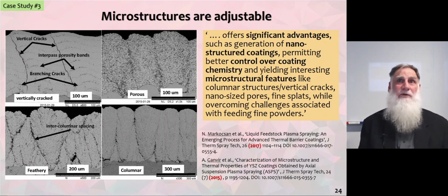And again, they were using liquid thermal spray techniques, and by changing the process conditions from these 4 micrographs, you're able to see that the microstructure was vastly different, with either vertical cracks, interpass porosity bands, branching cracks, to porous coatings which seem to be reasonably homogeneous with regards to porosity, to intercolumnar cracks, very similar to those which can be produced by physical vapor deposition. So to quote from that paper, the liquid thermal spray techniques offered significant advantages for generating nanostructured coatings, better control of the coating chemistry, and microstructural features.